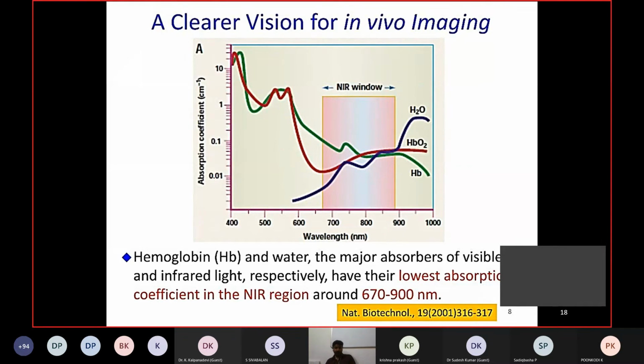So you can choose a wavelength that is suitable for heating only the nanoparticle. Selectively it will heat the nanoparticle. That best wavelength is 808. 690, 750, all these wavelengths were also tried earlier. Now it is understood that the longer the wavelength, the better it is. So 808 is commonly employed for photothermal heating, and there is another window above 1000. You call that the NIR2 window.